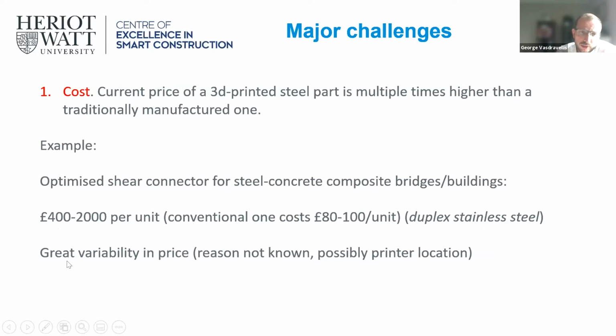We can see here we have great variability in the price. So I took 400, 500, 600, then up to 2,000. The reason, I don't know the reason, possibly it's the location of the country. Just one thing to emphasize here is that it is duplex stainless steel. Because when we 3D print steel, it doesn't make too much difference if we print carbon steel or duplex stainless steel. It makes sense to 3D print duplex stainless steel because, of course, it has many well-established advantages.